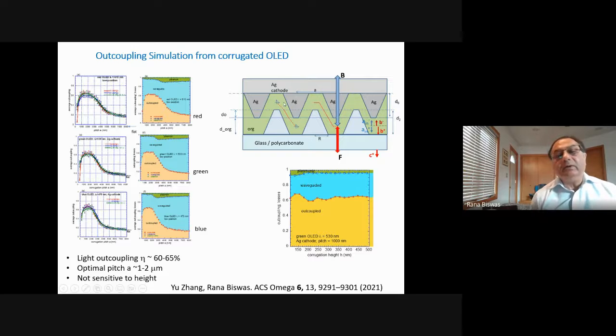So it's a very highly corrugated structure, and the emissive dipoles, like that nanocone, they sit in different positions. So they can sit at the top of the nanocone, or they can sit more towards the polycarbonate substrate. So there are different positions, and there are also different polarizations. So the sum result is that one wants to average over all the polarizations and average over most of the important positions.